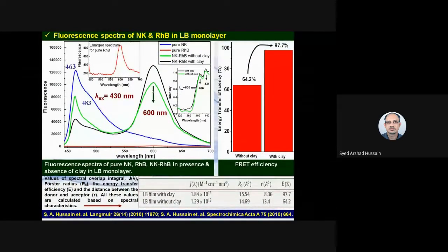And also when we incorporate them in thin films, energy transfer occurs. But in the presence of clay, energy transfer efficiency enhances from 64.2% to 97%.